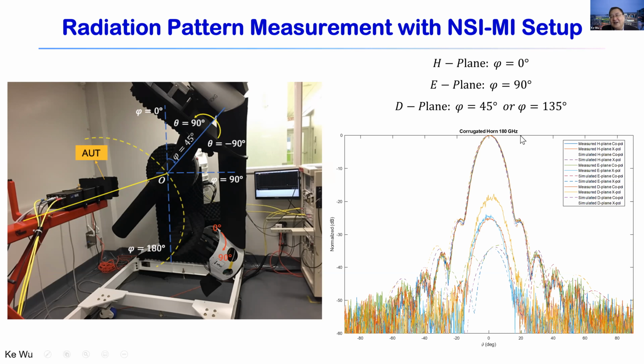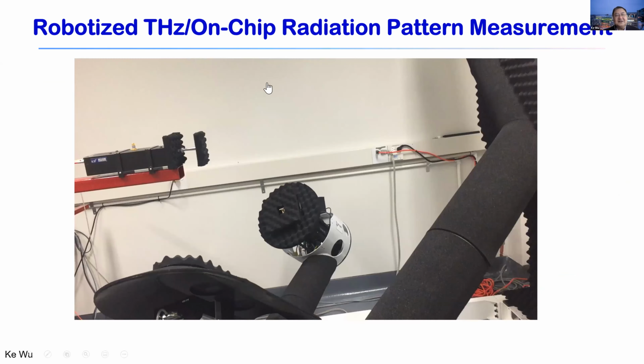So with this 180 gigahertz measurement, you can see 45 and 135 are the same, because those are the same angles. This is the co-pole and cross-pole, all the cross-pole measurements and simulation. The simulation and measurement results agree very well in this plot. That's really the high quality design we have made, except for the little defects at the 210 gigahertz region. This is the measurement setup, robotized terahertz optics on-chip measurements.